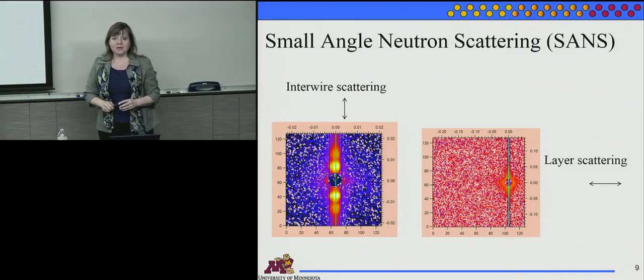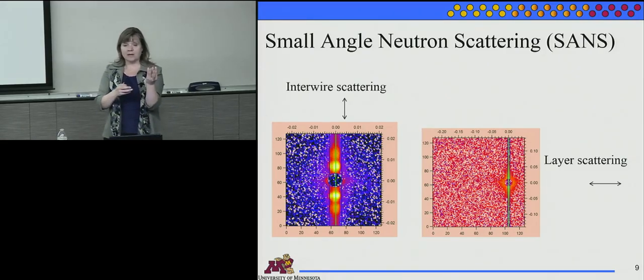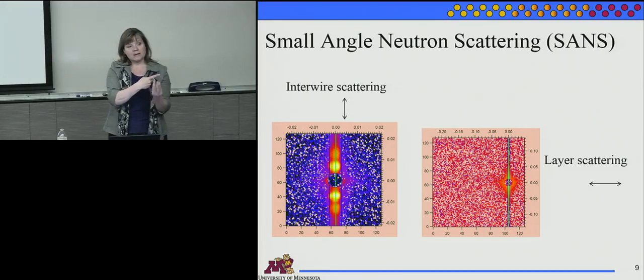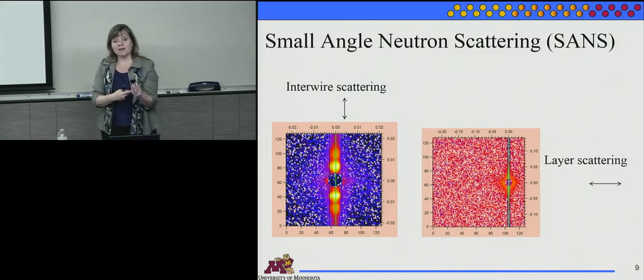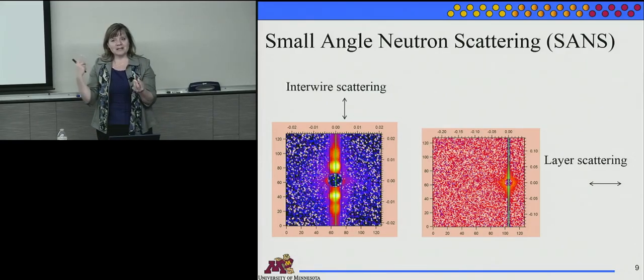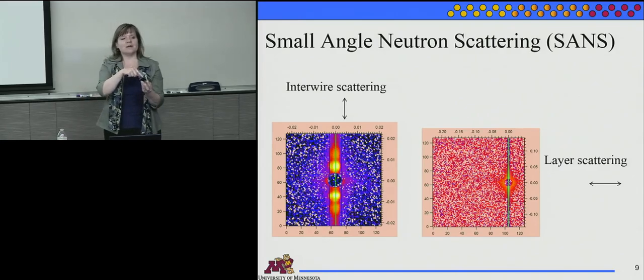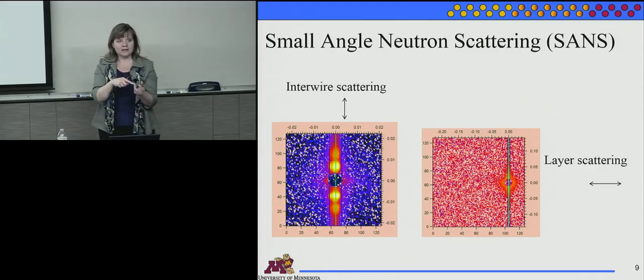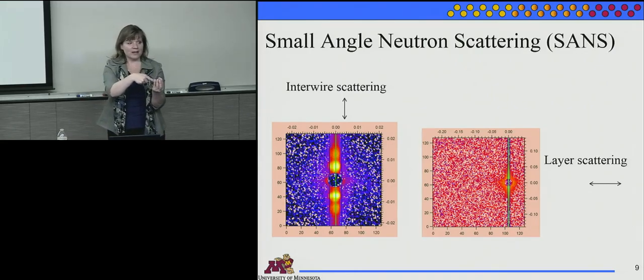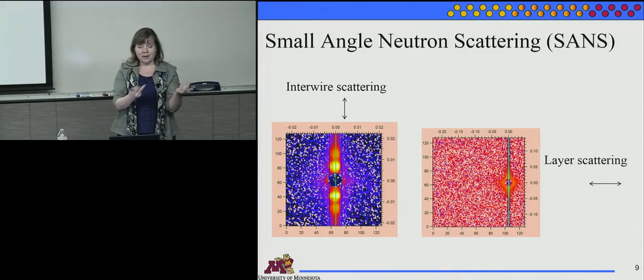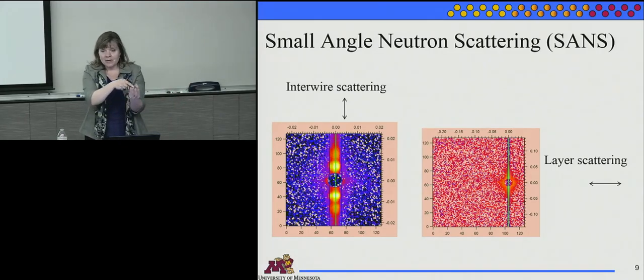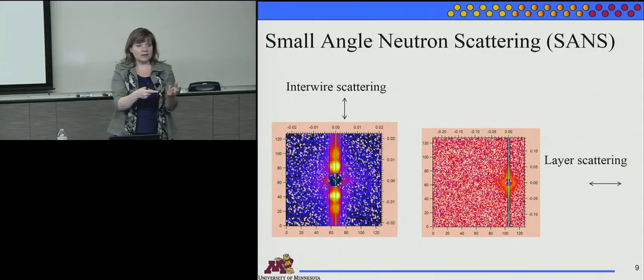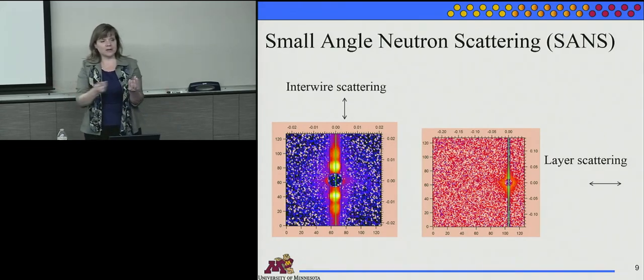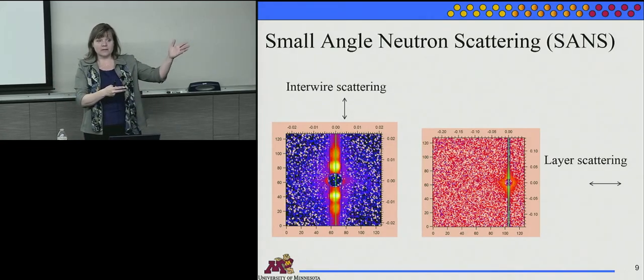All right, also small angle neutron scattering is very unique in that we can hit the entire sample of nanowires with neutrons. They are going to be sensitive to the magnetic moment, and it's very hard, really, even with the magnetoresistance, to even measure one wire. We've done it at times, but it's difficult. But to actually try to say what's going on inside that array all at once, it's opaque. You can't bring in a magnetic probe inside that. They're all very small. But neutrons, it turns out, if there's any kind of coherence, they'll diffract off of that.